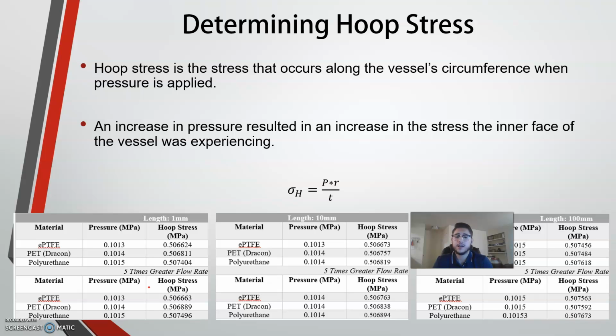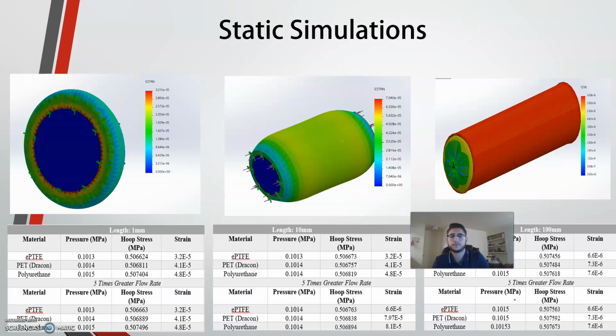As can be seen in the results, an increase in pressure resulted in an increase in the stress the inner face of the vessel was experiencing. The hoop stress for every material stayed in the half megapascal range. There wasn't much variation, as there wasn't much variation in the pressure as well. The hoop stress determined earlier was used as an input load in the static simulations for determining the strain values. Strain is a ratio between the deflection of a material against its original dimensions. As can be seen in the results, the models did not experience a significant deflection.